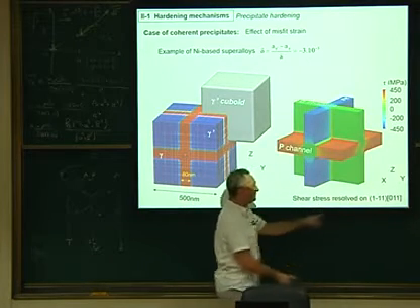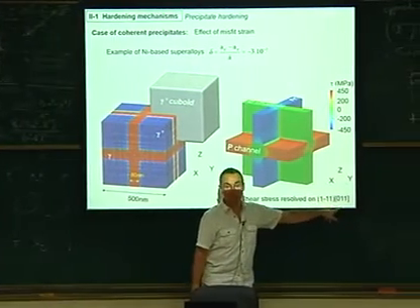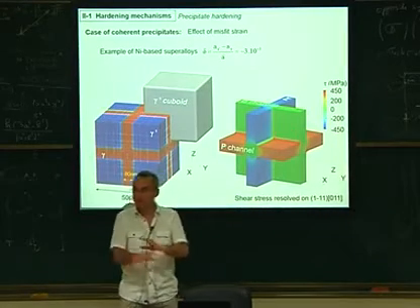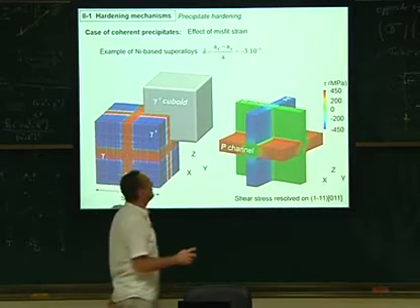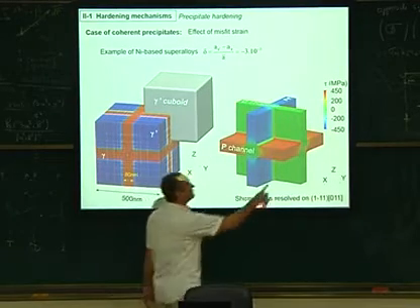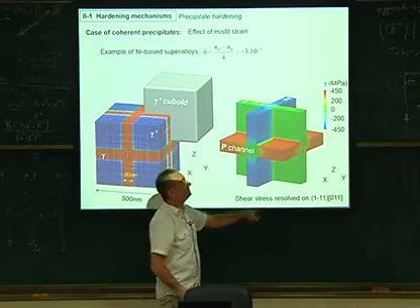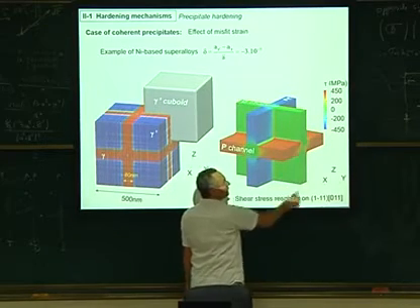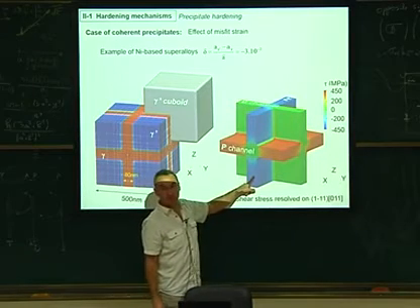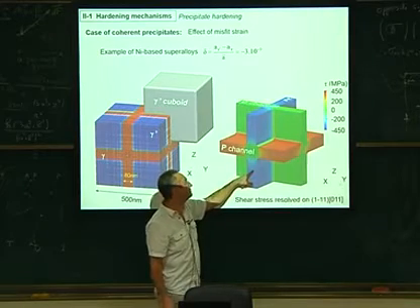So here what I plotted is the shear stress on one single given slip system. In that slip system, you have such a local internal stress just due to the misfit stress. Here there is no dislocation yet. It's just the initial stage. And you can see that there is what we call the P channel here, where dislocations can propagate easily because there is a huge stress, 400 megapascal. So here dislocations will move very easily for this system. Here there is one which is not active at all. There is zero stress, more or less, on that one. And this one is repulsive. Actually, it will push out the dislocation. It will not forbid the dislocation to come inside this particle if you pull on it.